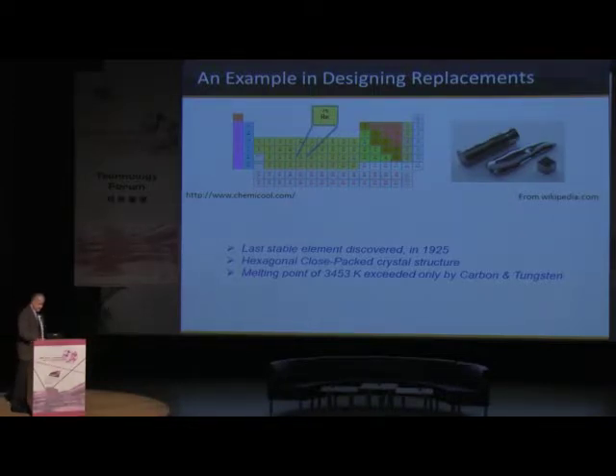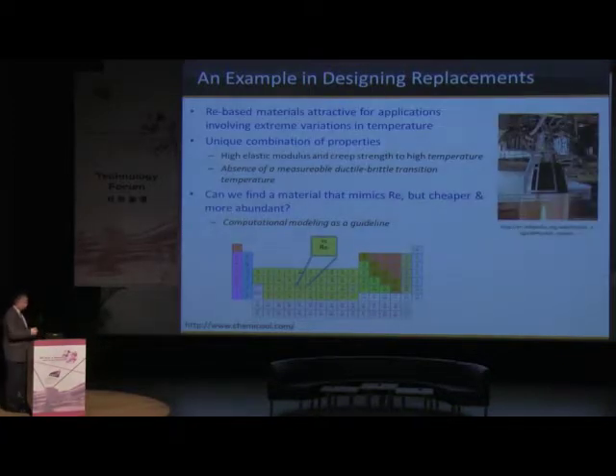Okay. Now, what's also interesting about this material is that it's very ductile. Okay. So it has very high strength at high temperature, but you can also form it. And if you're thinking about an application like a rocket nozzle here, it's particularly attractive because as the thing cools and heats and you have very big stresses, this material doesn't fracture and crack like other refractory metals. Okay, but here's the problem. Rhenium is extremely expensive and the worldwide reserves of it are very low. So if we really wanted to think about using it in more high temperature applications, we basically don't have enough of it around in the world.